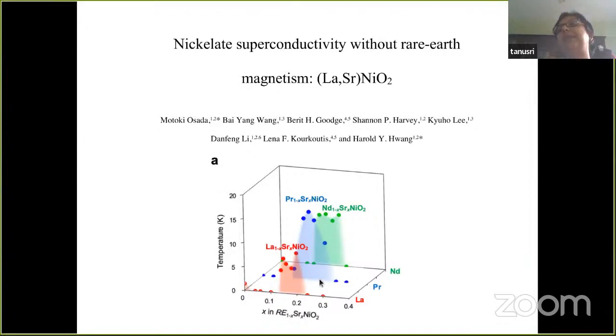And this is basically the kind of phase diagram that was reported in their paper. Of course, the details of this phase diagram, the details of the shape of the dome and so on, you cannot really have a quantitative agreement between what we propose and what they are proposing. But the interesting thing is they indeed find almost a factor of 2 separation between neodymium and praseodymium Tc at the optimal doping or the highest doping, because the shape of this dome is also quite tricky and funny. So it is a bit difficult to tell what the optimal doping is. But nevertheless, while the highest point of this dome is quite similar between the praseodymium and neodymium compounds, in the case of the lanthanum compound it is suppressed by about a factor of 2, as we have proposed.